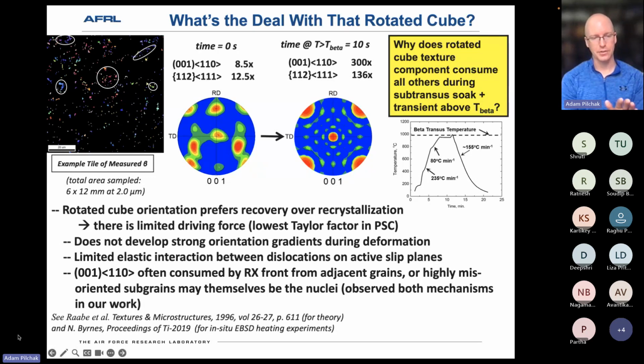Further, the slip planes that actually are active in that orientation have very little elastic interaction between them, and it's also been observed that those subgrains can be consumed by the recrystallization front of adjacent grains, just like we saw here. Or that the highly misoriented subgrains themselves may be the nuclei. So yeah, we saw both of those.